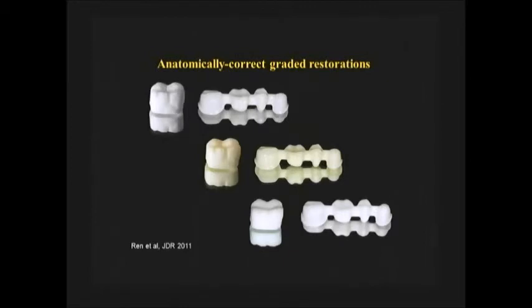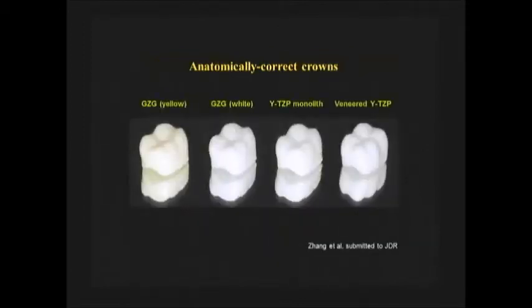First, I'm going to show you that with graded structures, we are able to tailor the shades. You can have white color shades and yellow shades, and we can also do somewhere between them. That's compared to monolithic, so-called single layer zirconia. We definitely have the advantage of providing shade variations. And these are single crowns, full coverage single crowns with graded yellow shades, graded white shades, compared to a monolithic zirconia and compared to porcelain veneer zirconia. So we are able to match the shades with these materials.